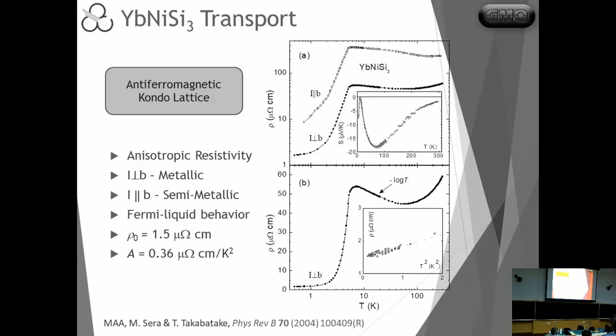Well, then as we started characterizing this new compound, what we discovered is that it turned out to be an antiferromagnetic Kondo lattice, which we could see through several different measurements. For example, right through the resistivity, we can see the signature logarithmic dependence here after a local minimum in the resistivity. It's a highly anisotropic one. You can see here that for the current parallel to B, it's almost like a semiconducting or semi-metallic material up there.